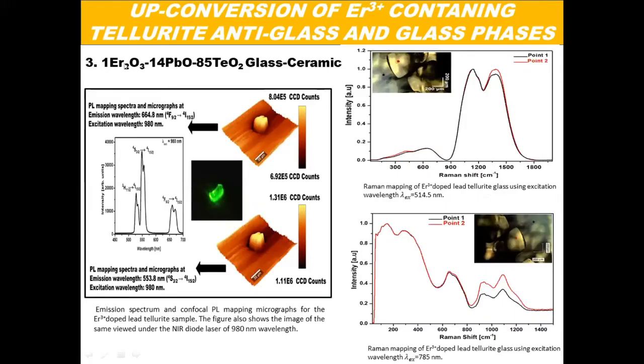Again, we add erbium oxide in lead tellurite glass ceramic, and we see upconversion again. The excitation wavelength is 980 nanometers, and we see green light emission of wavelength 553 nanometers.